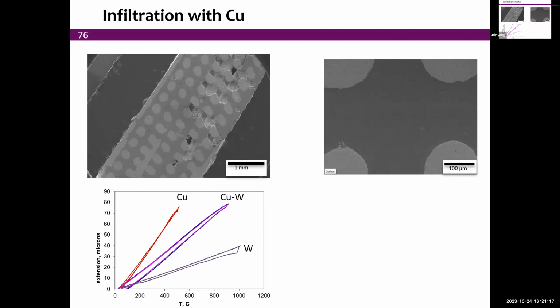And we do this mostly because we can achieve in the composite a coefficient of thermal expansion that is between that of copper and tungsten. This is the extension as a function of temperature. We see copper has a thermal expansion that is much higher than tungsten, reflecting the differences in melting points. And of course, the copper tungsten composite now has a thermal expansion that's in between those of copper and tungsten.